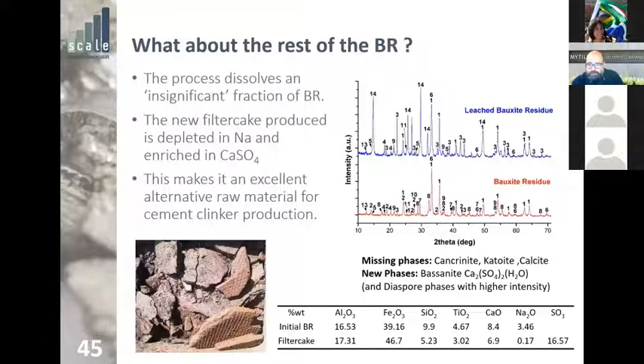You can see in the XRD to the right that we are missing all the phases that were created during the Bayer process, the secondary phases, like cancrinite, katoite, and calcite. And we have a new phase, bassanite, which is expected. At the same time, we can see that some of the original peaks from the bauxite ore, like the diaspore peaks, are now much more prominent. So effectively, what we have done is wash away the secondary precipitation from the Bayer process.